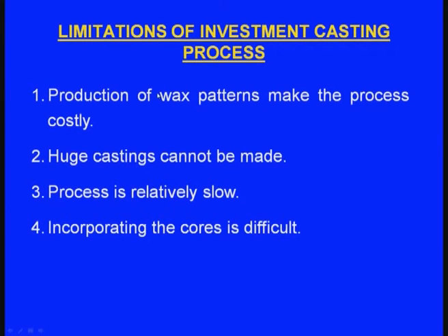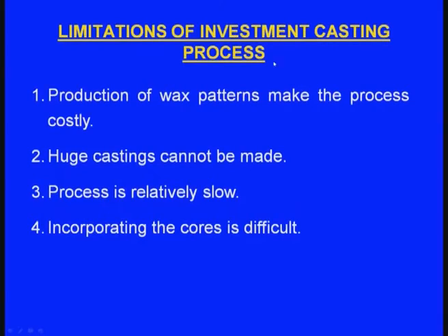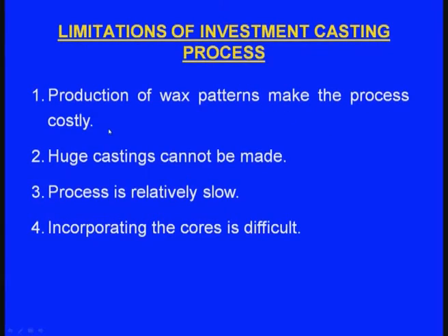Limitations of investment casting: production of wax patterns makes the process costly — wax must be blended with several other waxes and fillers, and shrinkage defects in wax patterns require rejection, demanding careful production. Huge castings cannot be made — in sand casting even 5-ton castings are possible, but in investment casting the limit is about 500 kg.